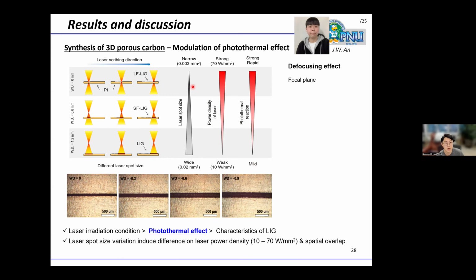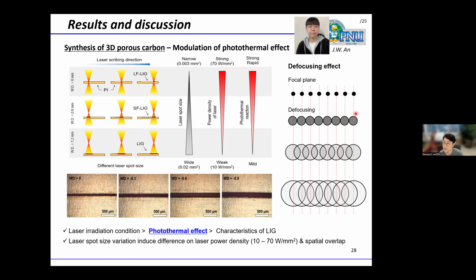In other words, under direct focus, high energy is concentrated within a small area. In contrast, under the defocus condition, the laser energy density per unit area decreases, and at the same time, the laser spots overlap, enabling the control of heat accumulation using this method. As a result, both the carbonization rate of polyimide and the degassing rate change, allowing us to tailor the LIG structure from porous to fibrous form.